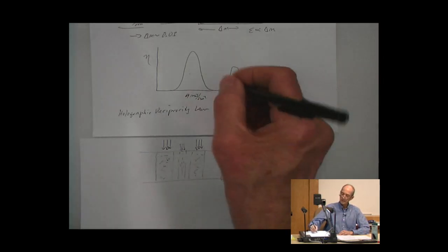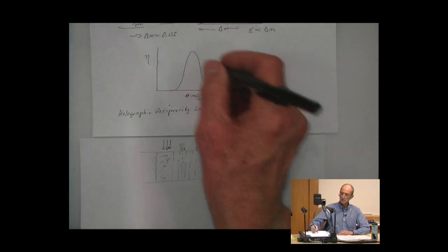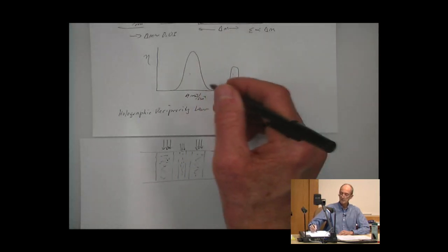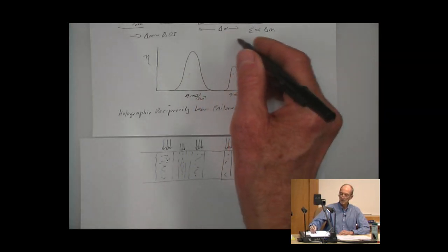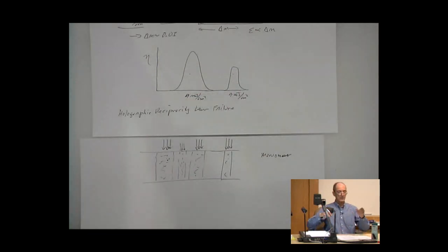Initially the second one might be lower, and then in the second case the second one might be higher. But that means you found the sweet spot. It's somewhere between 0 and 25% compensation that will give you the optimum reduction in the non-uniformity in the diffraction efficiency.